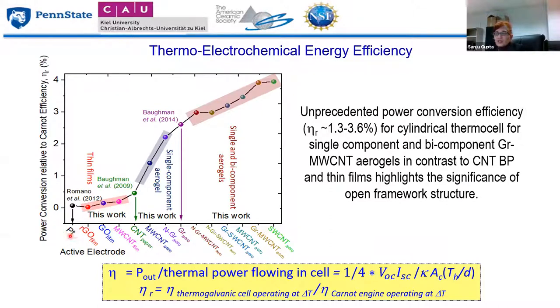I forgot to mention that the classic material for thermoelectrochemical energy conversion was platinum, but platinum is very expensive. So therefore we are looking for alternative electrodes. And it was also believed back then that the electrodes really don't play much of a role, which is not true because you need to have the ion transportation, and faster. So for some of these reasons, some groups are doing this research, and carbonaceous material once again is at the forefront.